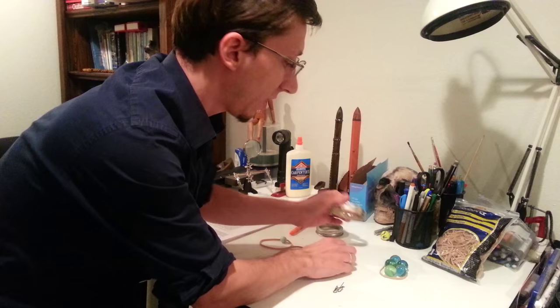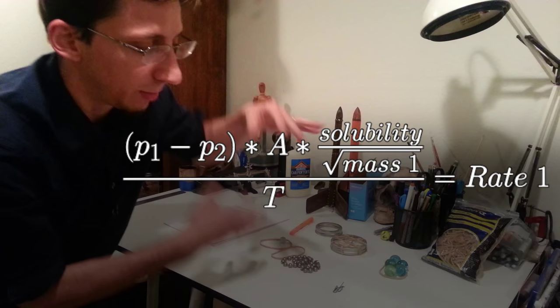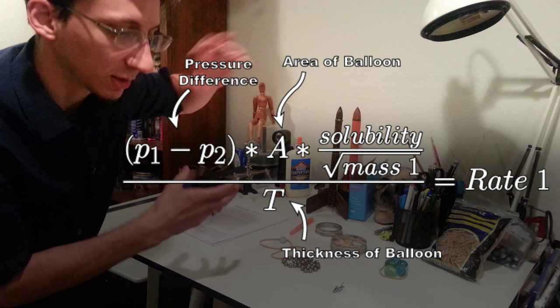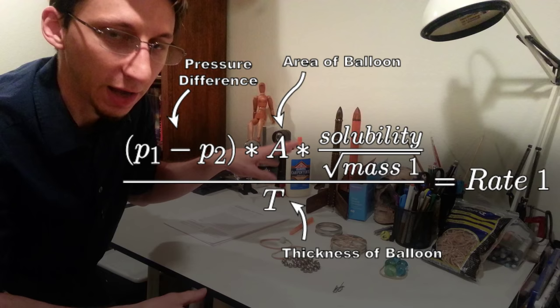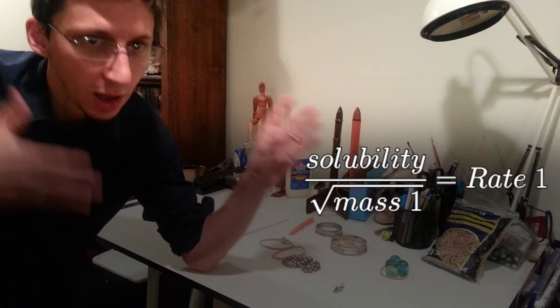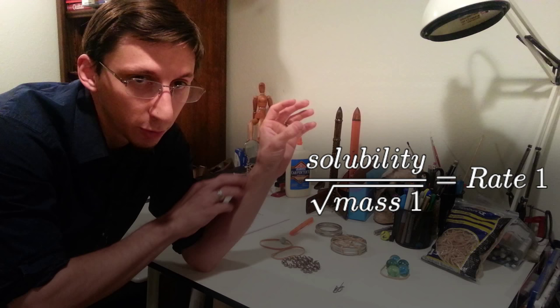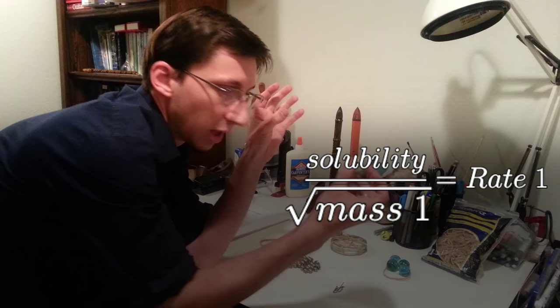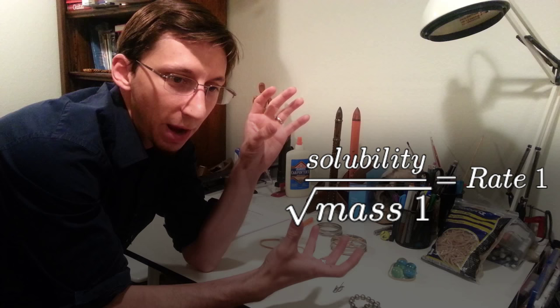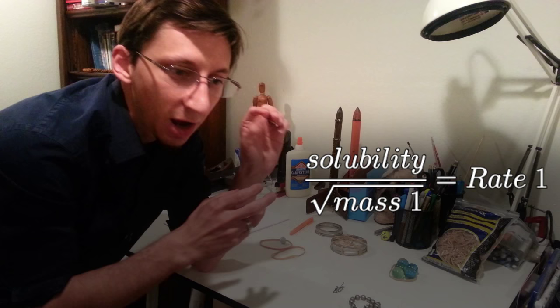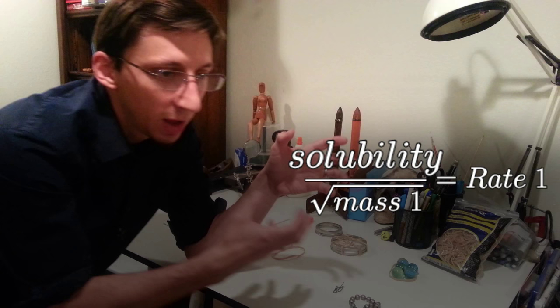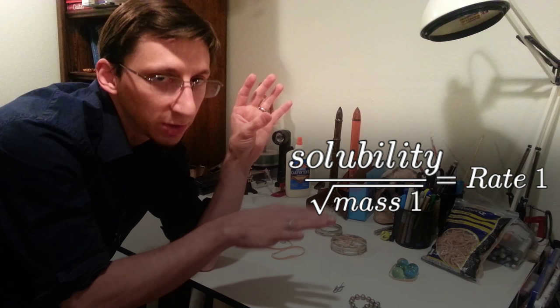And the way the mathematics actually works out, within Fick's law, you have this diffusion constant. This other stuff over here is like pressure and pressure difference and some other things. But the main thing, especially for a balloon where the pressure difference is really negligible, we just ignore that. So what's on the top is the solubility characteristic from Henry's law, and on the bottom is Graham's law of diffusion number, so that's the square root of the molar mass. So what ends up happening is if you get a large enough molecule like this, or one of these honking things, then it goes back to being primarily driven by Graham's law. But in this in-between range where you have the carbon dioxide and the difluoroethane that I was playing around with, the solubility term on the top has a much more important role than the minor differences in the molar mass on the bottom.